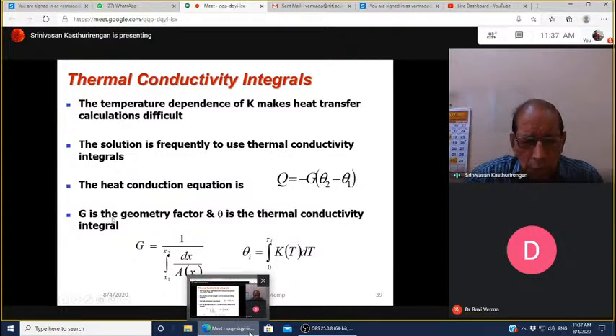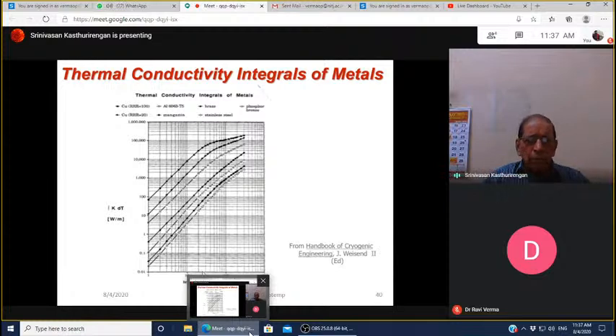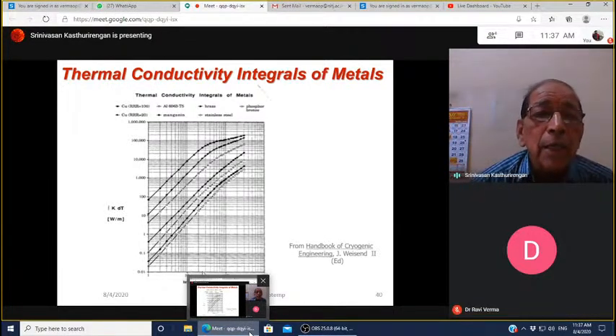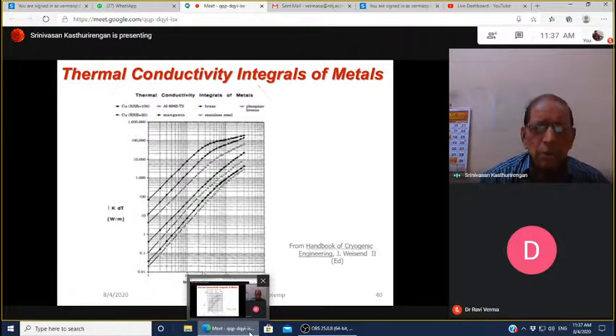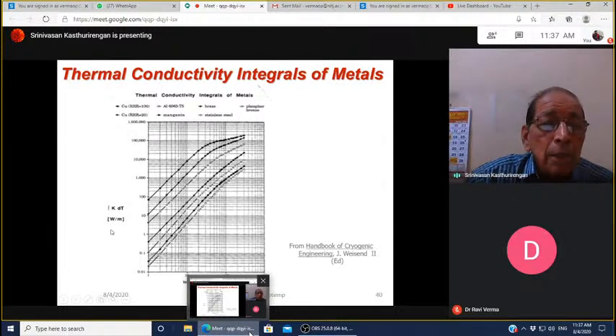The factor G is a geometrical factor, which is G equal to 1 by the integral from x1 to x2 of dx divided by A, where x is the material length from one position to another position, and A is the area of cross section. Okay. Now we can also have the thermal conductivity integral data available for different materials. This is from the Handbook of Cryogenic Engineering by Weisend. You can see various materials, some of which we discussed earlier: aluminum, brass, stainless steel, manganin, phosphor bronze, all plotted here. But now the units are watts per meter because it is the integral of K dT, as a function of temperature.